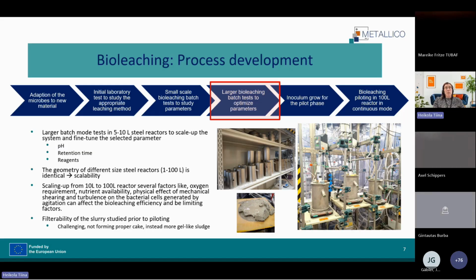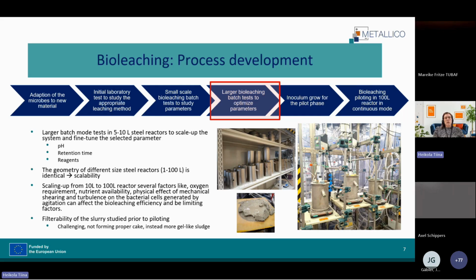For the piloting and the continuous phase run, we also tested the filtrability of the bioleaching slurry, and we noticed that there were some challenges during the filtration. So there was no proper cake forming. It was more like a gel-like sludge. So this was something that we needed to tackle as well.